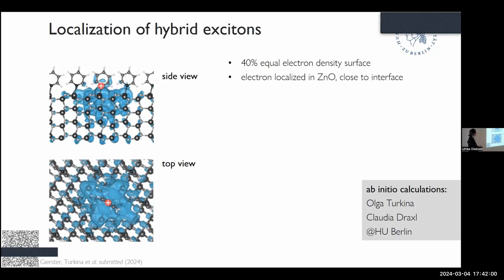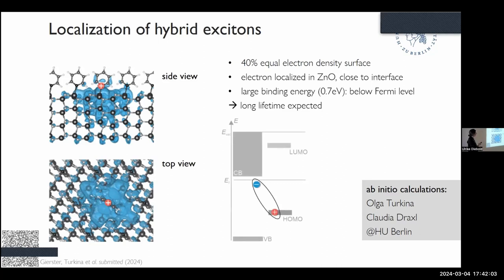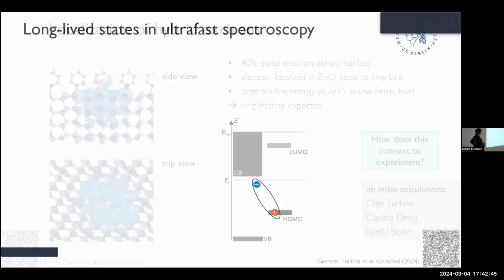Okay, so if we now consider an exciton with a binding energy of 700 millielectron volts with respect to the conduction band of the zinc oxide, this means that the electron needs to sit below the Fermi energy. If the electron sits in this exciton state, as you have just seen in the zinc oxide part of the talk, below the Fermi energy there are no decay channels because everything is occupied. So we expect again to see a very long-lived species with long lifetime.